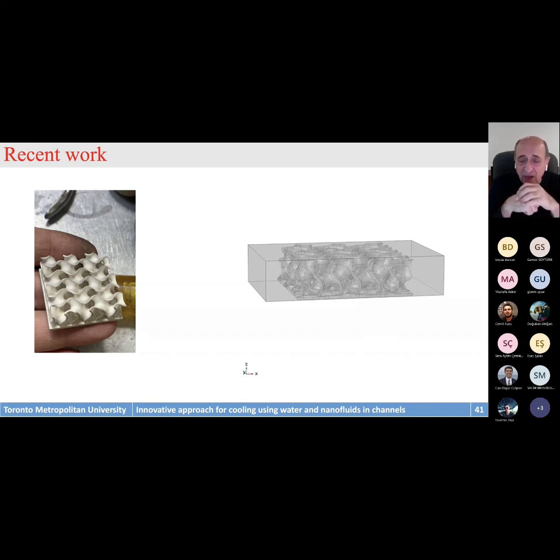So we tried to modify slightly and make the curves smoother, so that finally we were able to solve it numerically with our software COMSOL very nicely. And here you see the silver type of porous media. Now we have the capability of changing the permeability, changing the porosity. And when you do the modeling, we don't need to use Darcy or Brinkman or Forchheimer anymore. All we need to do is select in the model, this is a solid, this is a solid, and the gap between them is where the fluid will circulate.